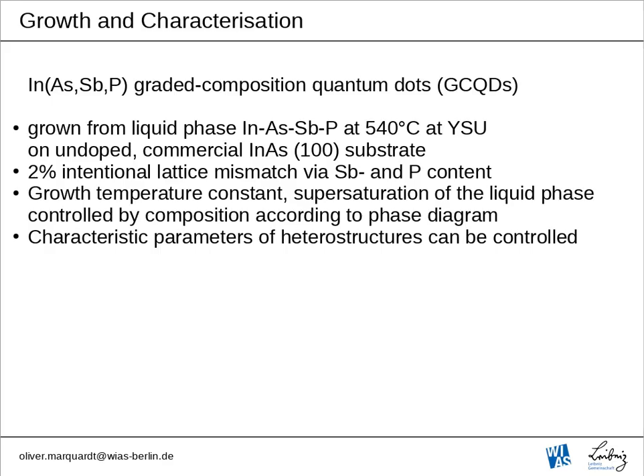The indium arsenide antimonide phosphide graded composition quantum dots that we are talking about here have been grown from the liquid phase of indium, arsenic, antimony and phosphorus at 540 degrees C at Yerevan State University, on undoped commercial indium arsenide substrate by my colleague Karin. There was a 2% intentional lattice mismatch, controlled by the antimonide and phosphide content in the initial liquid. A specific feature of our growth process is that the growth temperature was kept constant, while supersaturation of the liquid phase was controlled by the composition of the liquid according to the phase diagram.